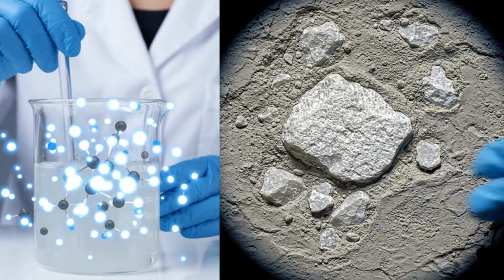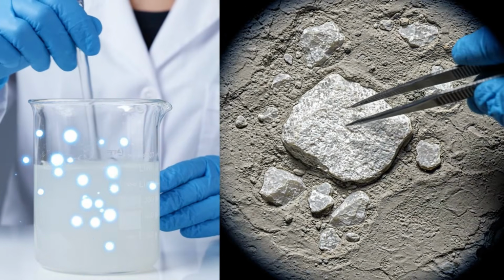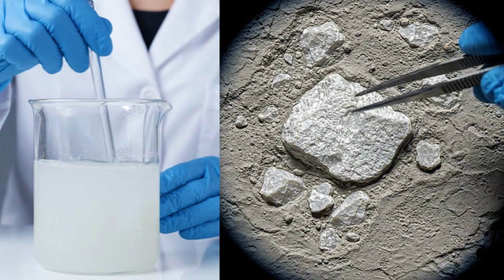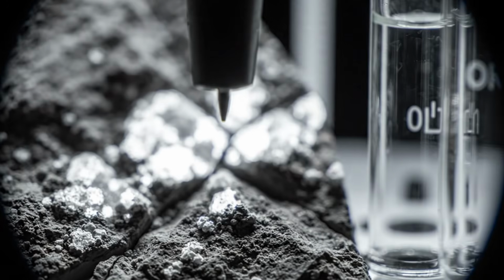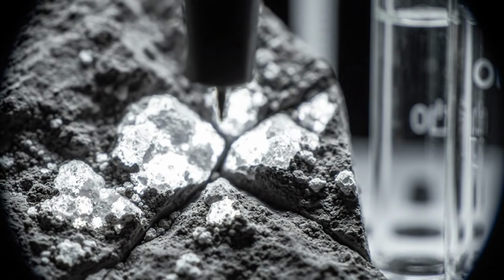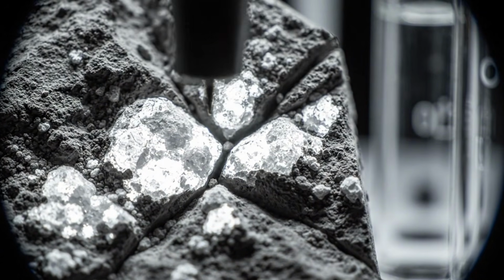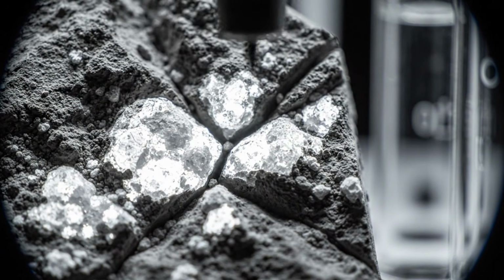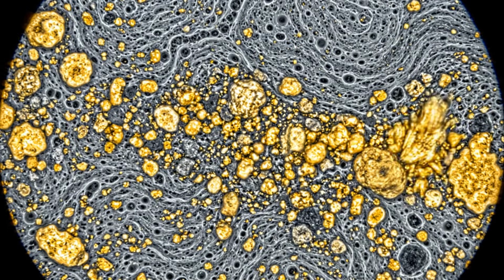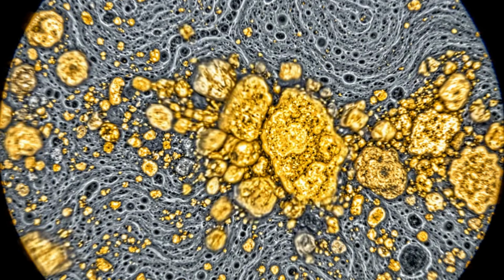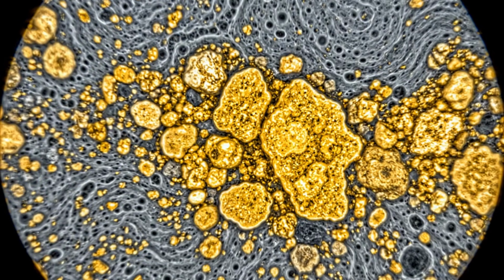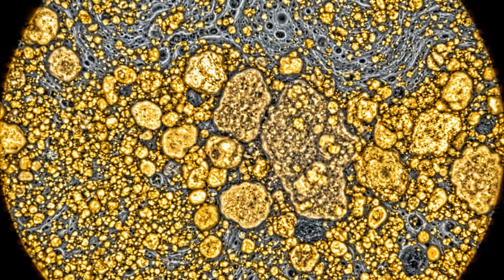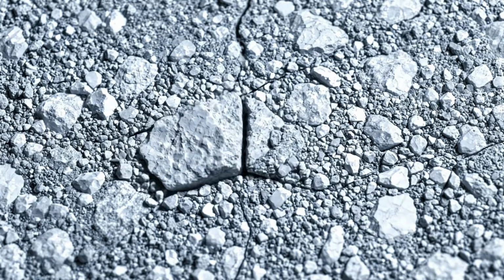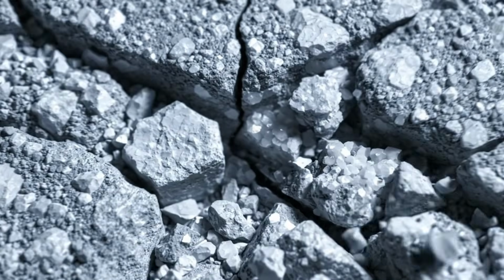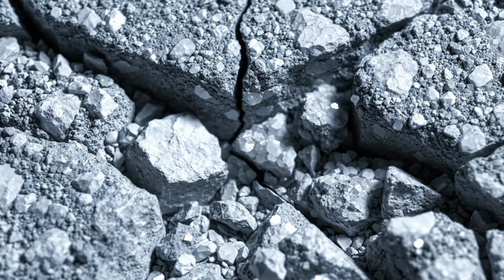Here is the structural consequence. In a conventional slaked lime mix, the lime dissolves and disperses. Hot mixing leaves the clasts embedded whole, and not as inert pebbles. They emerge brittle, nanoparticulate, with enormous reactive surface, concentrated deposits of calcium distributed through the structure like millions of tiny chemical warehouses. Now run a crack through that material.